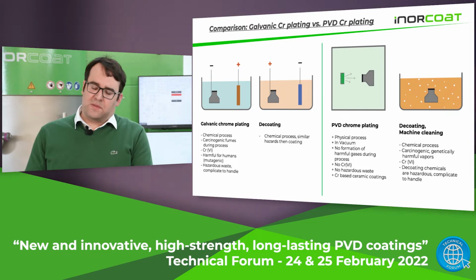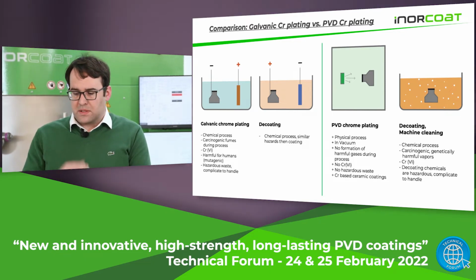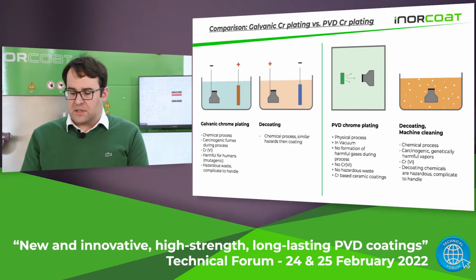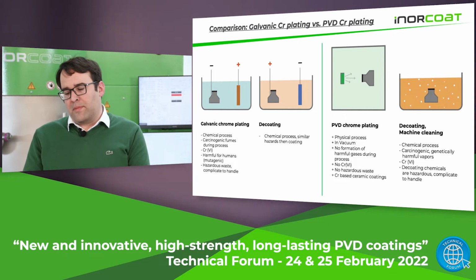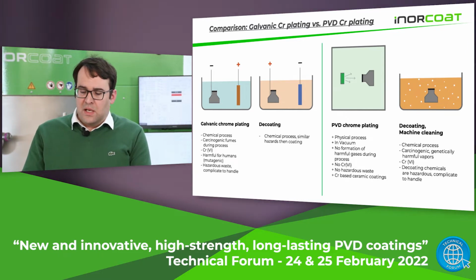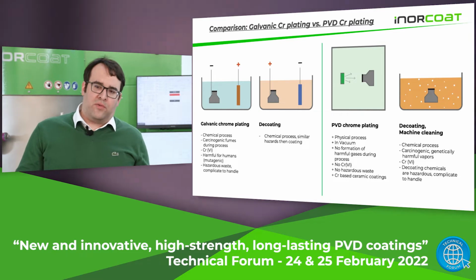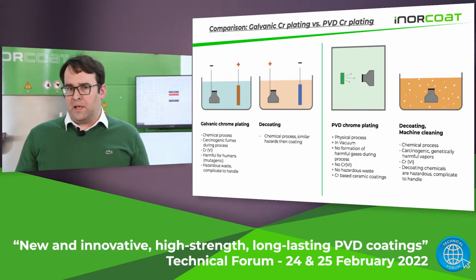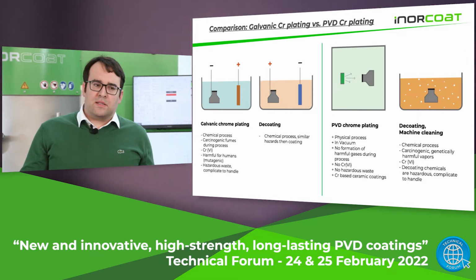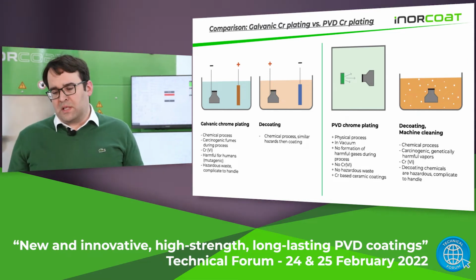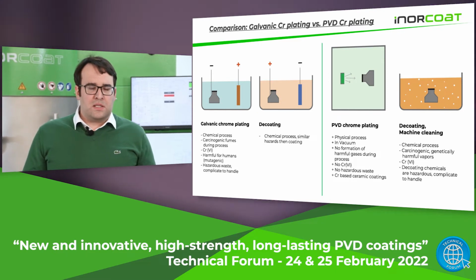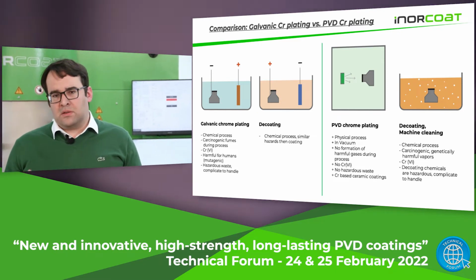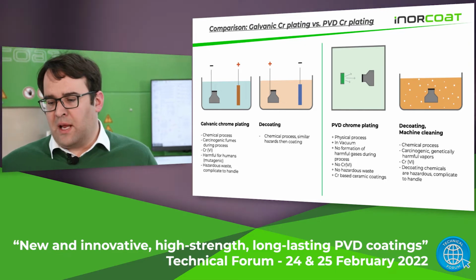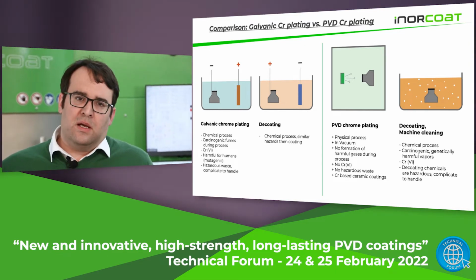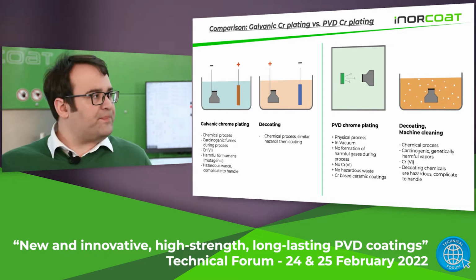So what are the problems with galvanic chrome plating? It's a chemical process. We have issues with carcinogenic fumes which are produced during the process. We have problem with hexavalent chromium, chrom-6. These substances are quite harmful for humans and are globally complicated to handle. The second step is where you are coating. It could be that you have also decoating. Decoating is similar to a standard galvanic process. You are using some chemicals and you have the same fumes which can exist like during the coating process.